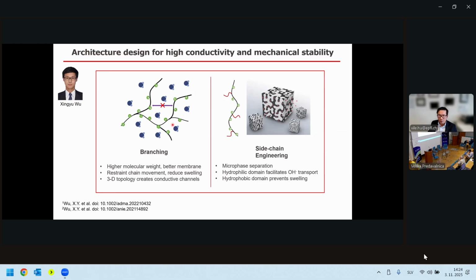This is good because with branching, you can typically get higher molecular weight, so you get a better membrane. But branching also somehow restrains the chain movement, so you reduce the swelling and increase the mechanical stability. In addition, when you make a 3-dimensional structure, we can control the morphology. You can create conductive channels, and that's good for conductivity. So this increases both conductivity and stability.